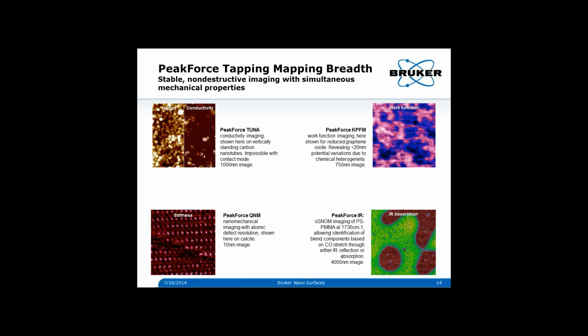These are all combining other techniques with peak force tapping, and so you get better performance of the integrated technique because peak force tapping is at lower frequencies than, say, if you were to try to integrate these with tapping mode. Also, peak force tapping works with pretty much any probe, allowing the probe to be optimized for the maximum signal in the technique. You don't have to use stiff probes in order to avoid adhesion issues like you do in tapping mode. And then also peak force tapping provides simultaneous quantifiable material properties along with the new thing that you're adding. So you really get some additional benefit there.